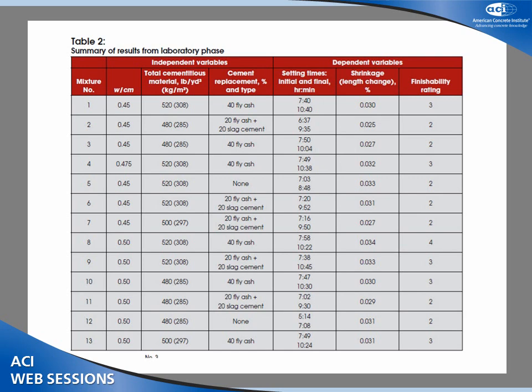You can see here the replacements. Mix 1 was 40% fly ash, mix 2, 20/20 slag and ash, and on down the line. The next column was the set times. Again, this is the critical piece of this research. And I want to point out down here that even in the lab, we had some reasonably close set times. And I'm going to point out mix 11 because this did even much better in the field. The next slide I'm going to show you is a field test of the four highest performing of these mixes.